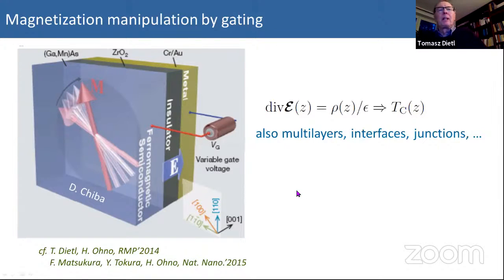And of course, we know for years that in such a structure we have to use the Poisson equation to describe the distribution of magnetization inside semiconductors. And now an interesting question arises, which also concerns multilayers, interfaces, and junctions, when we have inhomogeneous or non-uniform carrier distribution. How to describe TC in such an inhomogeneous system? TC depends on the carrier density. It's mediated by holes.